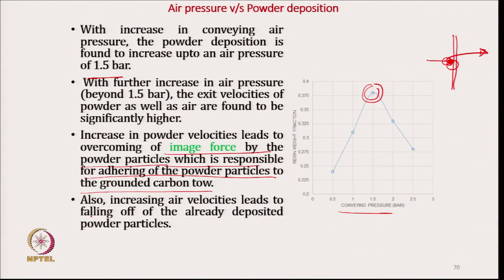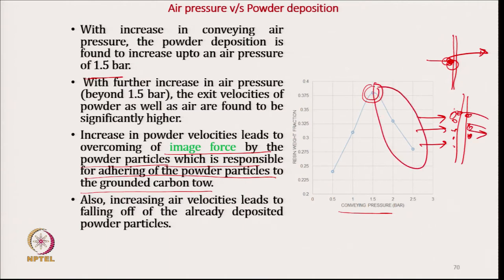In addition to that, further increase in air velocity leads to falling off of the already deposited powder particles. If we increase the conveying air pressure, the already deposited particles will get separated. So, this effectively leads to a decrease in the resin weight fraction. Initially we need some air pressure to help in deposition, but beyond a certain level, here 1.5 bar, it will overcome the image force which helps in attraction, plus the already deposited particles would get separated.